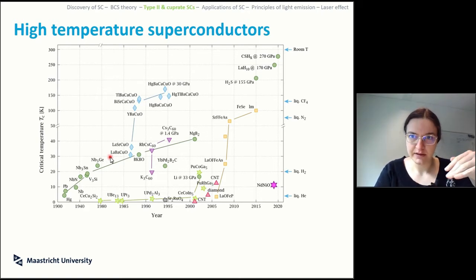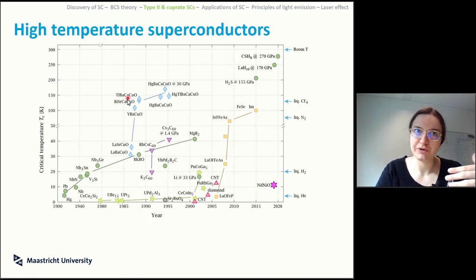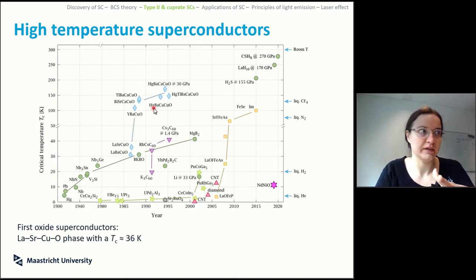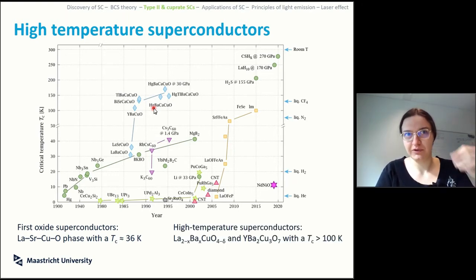But the big leap here was the synthesis of what is known as yttrium-barium copper oxide that had superconductivity at 91 Kelvin. So this is a real high temperature superconductor, because 91 Kelvin means that the superconductivity of this phase is achieved at liquid nitrogen temperature, not liquid helium temperature. And there are a series of modifications of these cuprates that can actually be achieved, while the very first one of this family has still low temperature superconductivity, which was supposed to be the standard. And then the high temperature superconductivity was the big breakthrough.